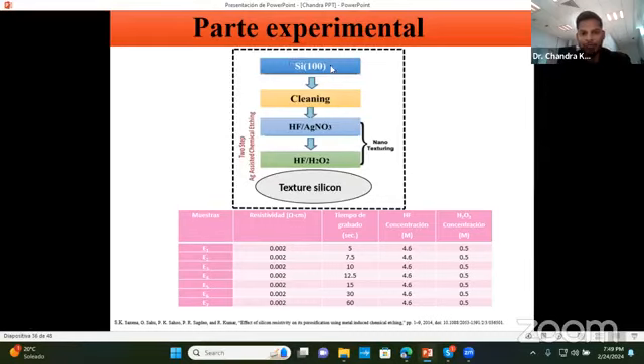If we take silicon, we have to clean it, and we can deposit silver nanoparticles. I will discuss later what the role of it is, but you can deposit through physical techniques like thermal evaporation, sputtering, electron beam, or through chemical means. It's quite simple to deposit through any precursor like silver nitrate, silver chloride, and later you have to etch with HF plus H2O2. So here are the conditions: we have taken different wafers with the same resistivity, and this is the etching time.